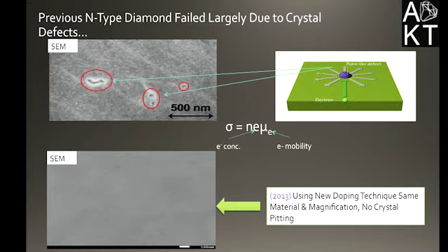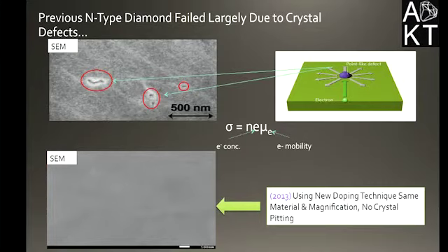So if we're trying to think about diamond and the use of electronics, not only is it an issue from a conduction standpoint, but having these potholes also makes it very hard to have smooth contacts for metallization and the like. But in 2013, a new doping technique was shown that, utilizing that same single crystal material under the same magnification, incorporating the same amount of impurity atoms, we see no crystallographic dislocation.